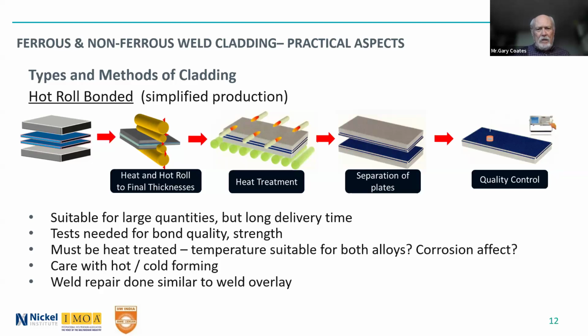This clad method must be heat treated. To do that, you have to choose a temperature that is suitable for both the backing material and the CRA layer. And usually there are some differences in what is ideal for both. So you have a compromise temperature, and then you ask what is the effect on the corrosion resistance, if that is what you're using it for. You have to be very careful with hot and cold forming that in that operation you don't separate the two layers. And of course, weld repair, if you need to do weld repair, it's really done in the same way that you would do a weld overlay.